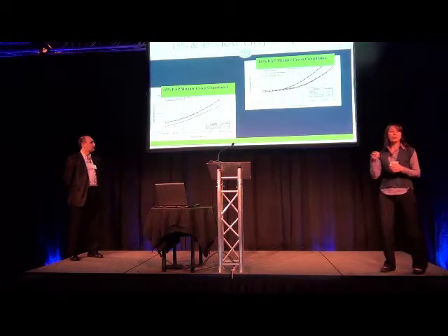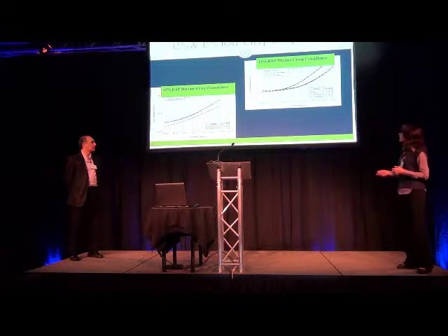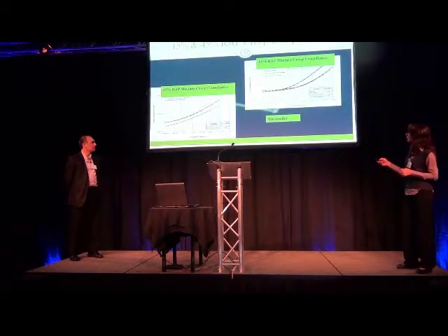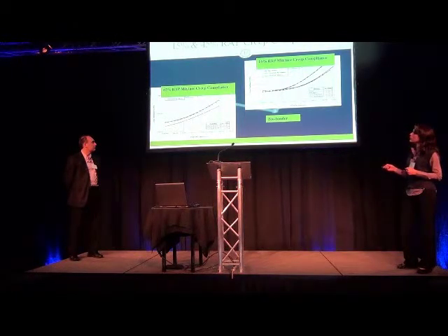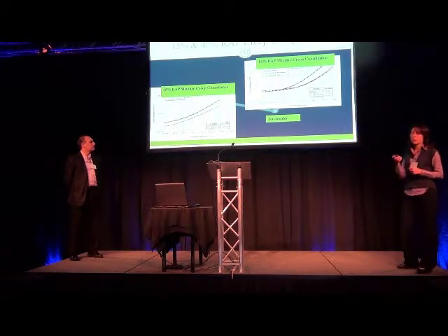And then we started adding more recycled material, recycled shingles, and so forth, to see how far we can push the envelope using this material. So for example, this one is the creep compliance curve, and this is with 45% recycled material. That's the curve with adhesive. This is a control. The red is control. Same thing here. The red is control, and this one is our adhesive. So with 15% and 45%, we had very good success in matching the control properties. So basically, you have 45%, but it behaves like there is no recycled material.